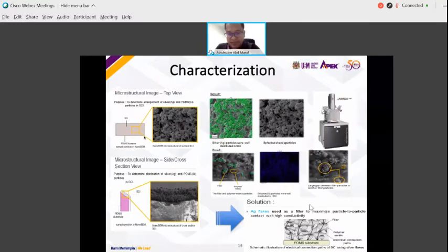So from here we do some studies on mixing, because the mixing ratio will determine how good your conductivity is. If you increase the silver nanoparticles, of course conductivity will increase, but they will increase the cost of your ink. If we use a lower ratio of silver nanoparticles, it will reduce the cost of the ink, but of course it will decrease the ink conductivity. So this is the trade-off.